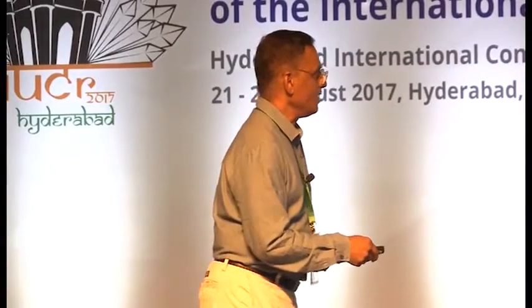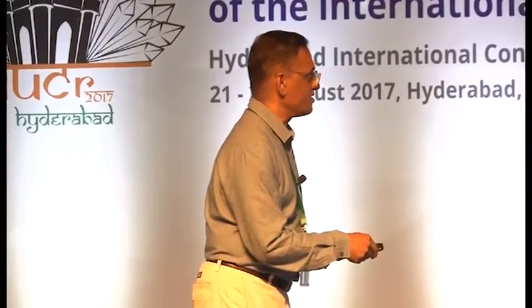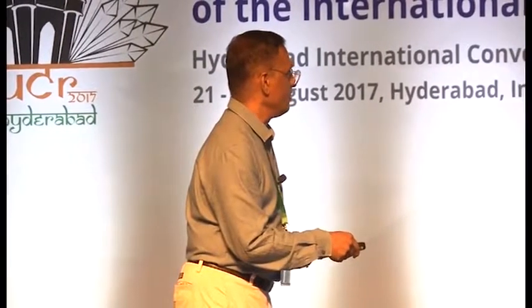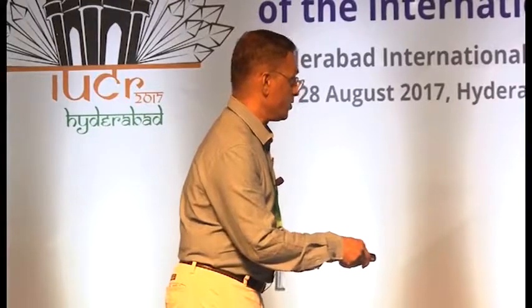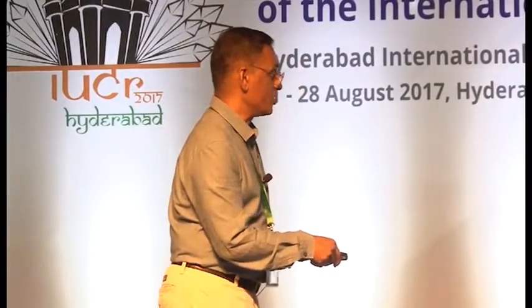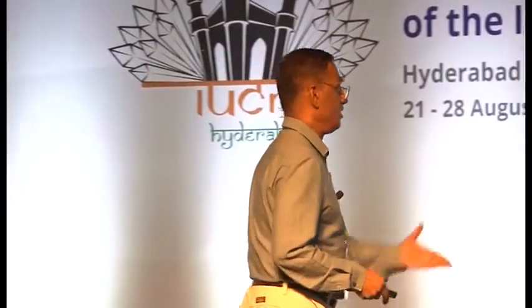of these optical studies. We made this ladder structure that has the same ligand, which I mentioned. We also have benzoates, as a bridging ligand, as well as chelating ligand. The structure is shown here. This particular compound shows third harmonic generation. As I mentioned to you, it's very strong, okay? And also it shows 2-photon, 3-photon, and 4-photon emission. In addition to it, it shows second harmonic generation, all in one. The same crystal shows all these properties.